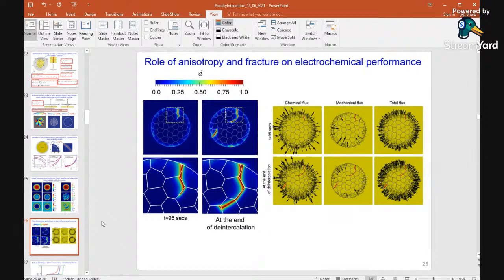The crack is developed from the outside, the particle matrix interface, because the highest amount of tensile stress is developed there, which is a circumferential tensile stress. And if you see, at the end of the deintercalation cycle, you can see clearly that some of the cracks enter the crystal, within the crystal. So it's not completely a grain boundary fracture, it is also within the crystal, and that is driven by the energetics associated with the fracture problem. So it's not necessary that it will always go through the grain boundaries, although those are weak sites. It is more about how the energy is fed into the fracture process.